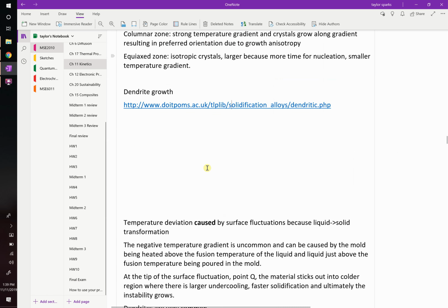Yeah, it's one of the classic things I hope you take out of this class. If you do anything that makes it harder for a dislocation to move through this material, you made it harder and less ductile, right? So these steels are going to be much less ductile than if you grew those really columnar grains in them, which are going to be more ductile, but at the expense of being much weaker, okay? All right.